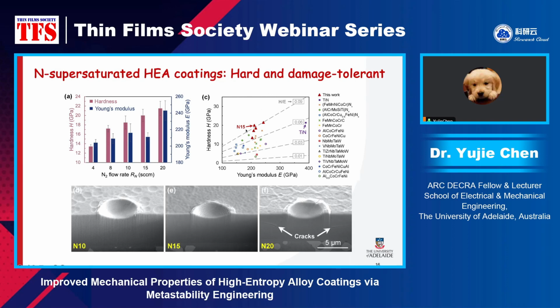We also looked at the H/E ratio. This H/E ratio is an indicator of resistance against the elastic strain failure, which has a good approximation to rank the fracture toughness of hard coatings. As we can see from, it's an H-E type plot, and this point is N15. It has a very high hardness value, which is comparable to ceramics.